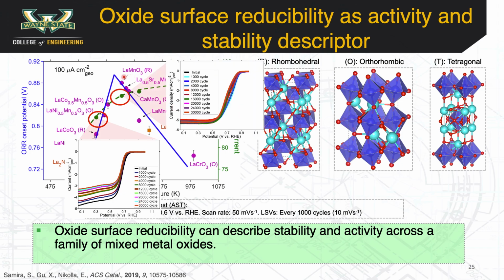An oxide close to the top, like rhombohedral LaMnO3, provides an optimal compromise between activity and stability. LaMnO3 meets the DOE criteria of less than 40% loss in activity over 30,000 cycles, thus making it active and stable. This suggests that the oxide surface reducibility can be used to describe activity and stability across a family of